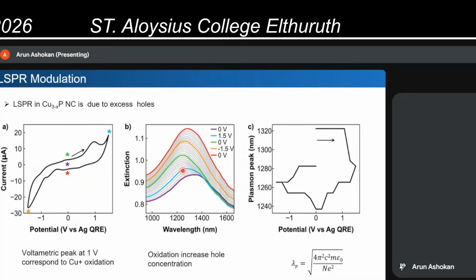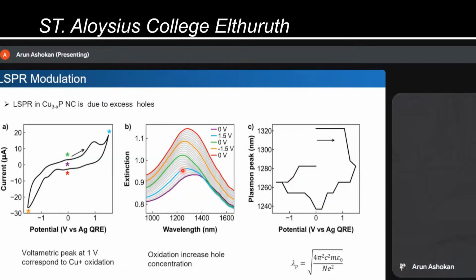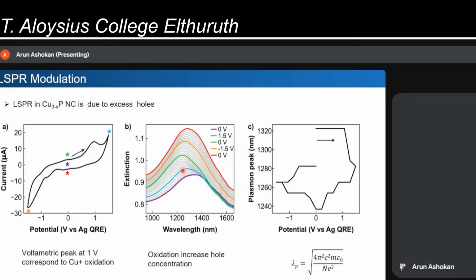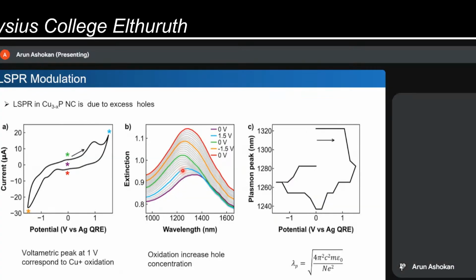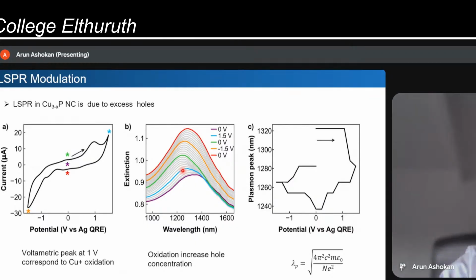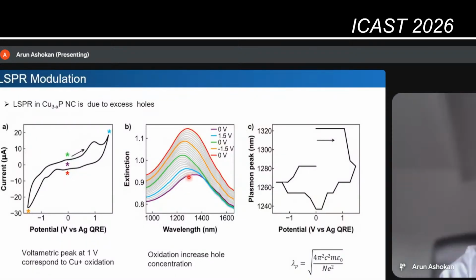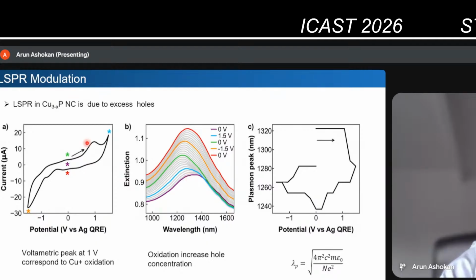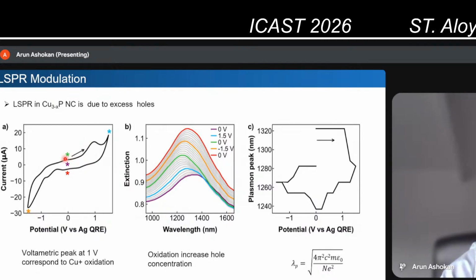So the difference is basically it's blue shifting, slowly blue shifting. And then we are switching the potential. We are scanning backwards. We came all the way up to here. Again, back to zero. That's the green one. So at green, it's still blue shifted, compared to the initial open circuit potential plasmon peak. And now we are reducing it again.